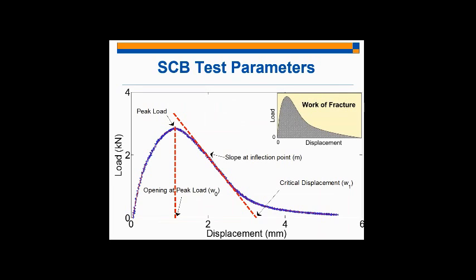Additionally, the other parameters we extract are the peak load, which can be seen there, then the slope at the inflection point. So past the peak load, I'm looking for my first inflection point in that post-peak softening portion of the curve, and I calculate the slope of the line fit through the first inflection point, and that gives me my value M, my slope value. Then you can see the critical displacement value, which is basically where that line fit through the inflection point intersects the x-axis. And then finally, you can see the opening at peak load, which is simply the LVDT displacement at the peak load. So these are the parameters of interest.